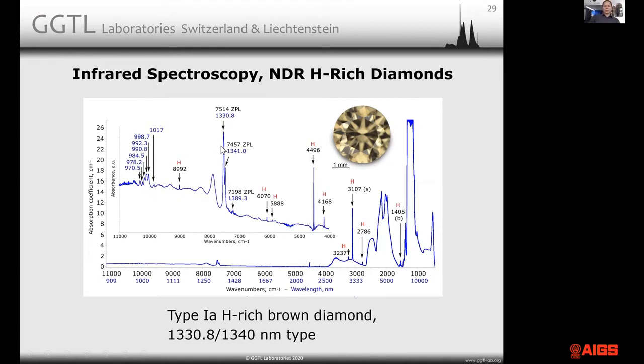I'm not sure if this center is the actual cause of everything that happens afterwards in the visible. When you look at the whole spectrum, which we've also done, normalized all the way to the visible, the band here in the near infrared is by far the strongest feature of the entire absorption spectrum from the near infrared all the way to the UV. To my knowledge, I have not seen a low temperature spectrum of it yet. So this is a very, very interesting spectrum, and it actually defines this type for us. We call it the 1330.8, 1340 nanometer type.